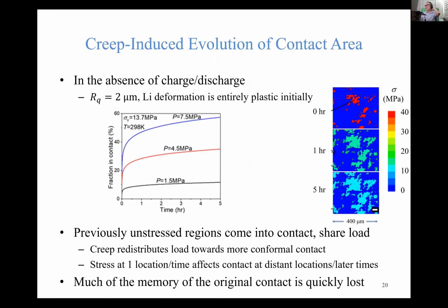So this shows a little bit like what creep-induced evolution of the contact area looks like. Initially, you might have very high stresses, so you have very fast creep, and the contact might look like this. After an hour, the creep has redistributed where the lithium is. It's redistributed the load toward more conformal contact, and therefore the stress locally is going to go down, and therefore the creep rate is going to fall drastically.